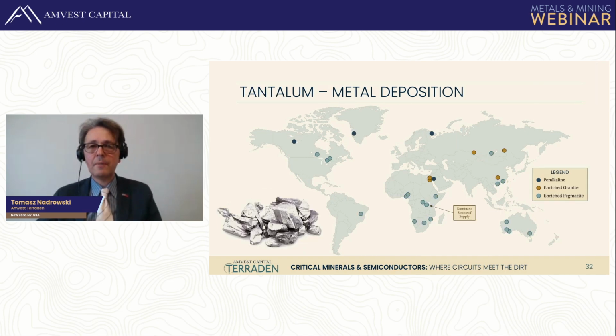Here's another metal that's mostly used as a barrier metal, although also appears in gates. This is tantalum, so it separates copper from silicon. Has thermal stability, is highly conductive, also protects the elements from corrosion. Here, again, China is not very dominant. Most of the production comes either from peralkaline or pegmatite deposits and from coltan, so columbite-tantalite, associated with niobium in Rwanda and Democratic Republic of Congo.